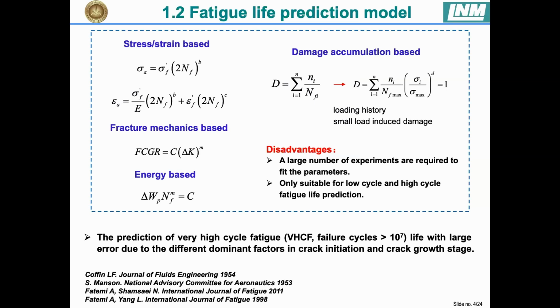For fatigue performance, fatigue life is one of the strictest indexes to evaluate. But the traditional fatigue life prediction models, like stress, strain, fracture mechanics, energy, and damage accumulation-based methods, all need a large number of experiments to fit the material parameters to get more accurate results. They are also only suitable for the prediction of low cycle and high cycle fatigue life. But in very high cycle fatigue, which corresponds to failure cycles exceeding 10 million cycles, we expect a larger scatter due to the different dominant factors in the crack initiation and crack growth stages. Therefore, in this study, a pore-based prediction of crack initiation life in very high cycle fatigue is proposed.